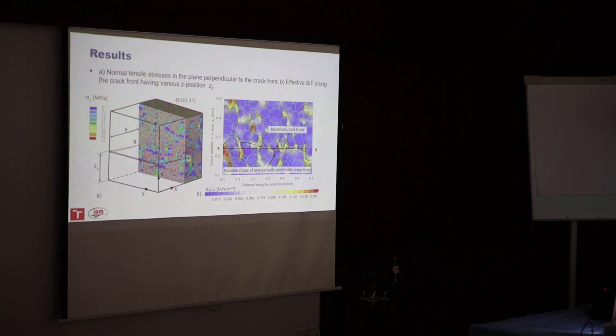We did also calculations when we moved the crack front in vertical direction. We calculated for all possible positions of the crack front what will be the stress intensity factor, corresponding stress intensity factor of the crack front. We see here that there are locations where it's relatively high and this location corresponds exactly to positions of the small grains where tensile opening stresses are present. So in fact, in reality the crack will not propagate in a straight line because it's not energetically convenient for it but it will follow the path where it will be the most effective for it. So in fact it will be the path where the opening stresses will be the highest.